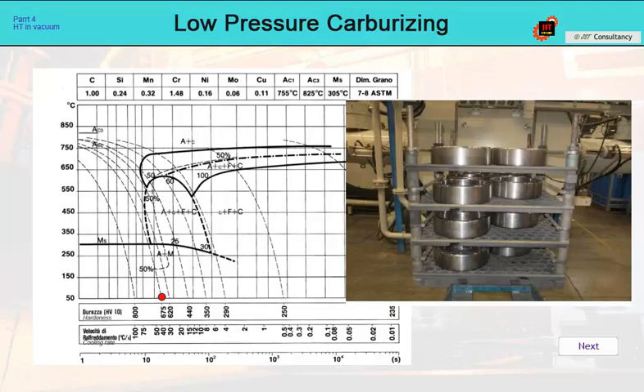However, since the total load can behave quite differently, the critical limit between hardenability in oil and in the gas stream must always be verified in advance. It's not that simple. The figure shows a CCT diagram for 100Cr6 bearing steel. In order to quench the parts properly, we must have a cooling rate of at least 40 Celsius per second. The result is in the picture.